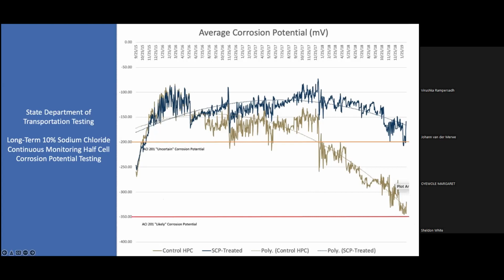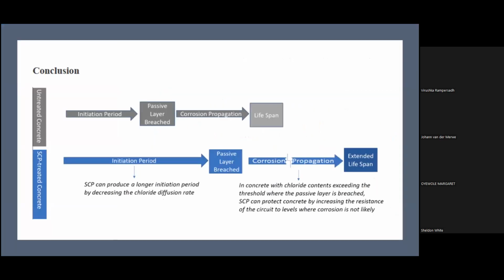And you can see that it was not performing that well up to the 3 year mark. So the way that colloidal silica can interrupt that corrosion cycle is, number one, it can slow down that initiation period by slowing the chlorides from getting to the reinforcing steel. And then it can also shut off that external source of water that the Neville model indicates is necessary for continued self-sustaining corrosion. So in those two ways, colloidal silica can extend the life of concrete.